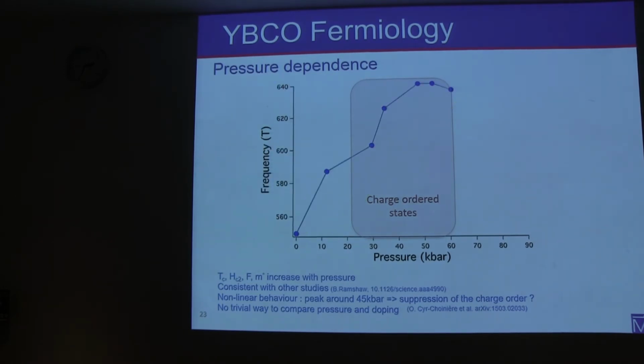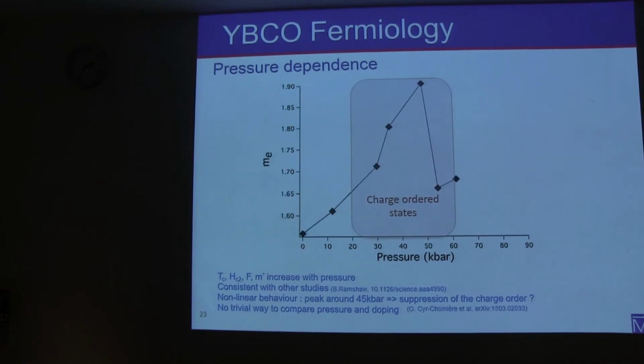The frequency of the quantum oscillations again shows something happening in that region of the pressure. And again for the effective mass. So all of those quantities show a non-monotonous behavior in the pressure range of 30 to 55 kilobar. And we attribute that to the effect of pressure on the charge density wave.